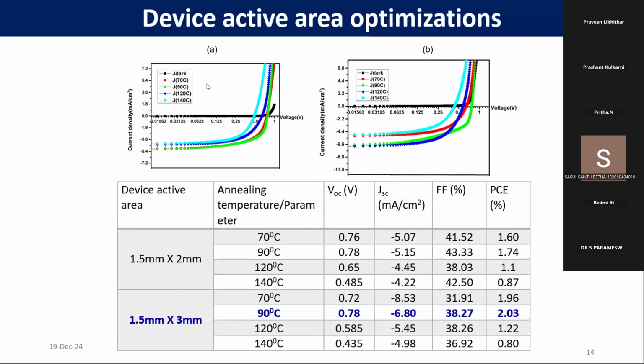And we also need to consider the device active area. Whatever I'm talking about here is all about the photoactive layer. So what is the active area at which one can obtain the highest power conversion efficiency? Here we tried different active areas, 1.5 millimeter by 2 millimeter, and then 1.5 millimeter by 3 millimeter. At 1.5 millimeter by 3 millimeter, 90 degrees Celsius was giving the highest power conversion efficiency, that is 2.03. So these are all parameters one needs to optimize in order to get the highest power conversion efficiency of the solar cell device.